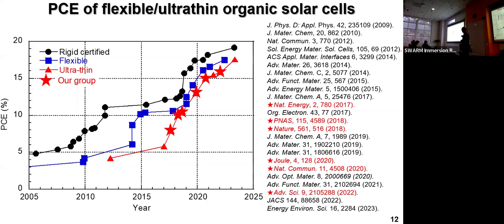Recently, the PCE using a very thin substrate was reported by the Zhejiang University research group. So currently, we are not the best. Unfortunately, we are trying to be the best again. But anyway, recent research improved the PCE of both flexible and ultra-thin organic solar devices dramatically, from less than 10% to around 17%. So a dramatic improvement was achieved within these 10 years.